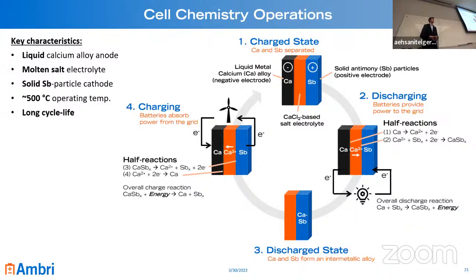Yep. Does the high temperature and the liquid phase increase the internal cell resistance, which might limit power density for charge and discharge speeds? So really the reverse. High temperature lets you overcome kinetic barriers more easily. And so the reactions are extremely facile, that depositing liquid metal at these temperatures has very little overpotential. The dominant form of overpotential in our battery is the resistance of the ions through the electrolyte, which is not very high. So we're actually able to operate at hundreds of milliamps per square centimeter compared to some lithium ion batteries, which might be 5 or 1 milliamp per square centimeter.